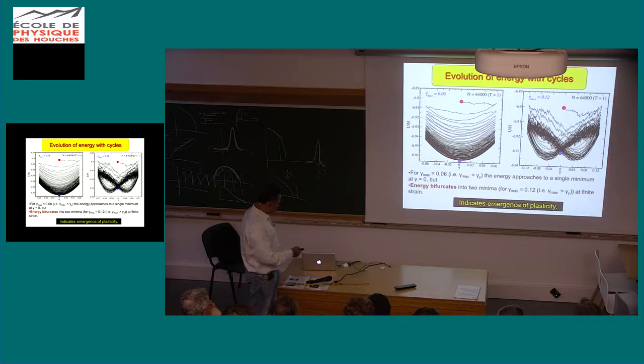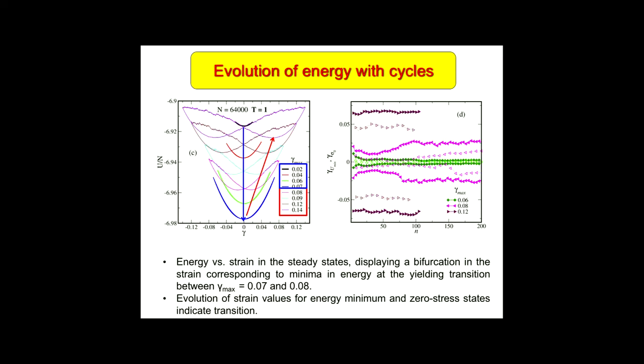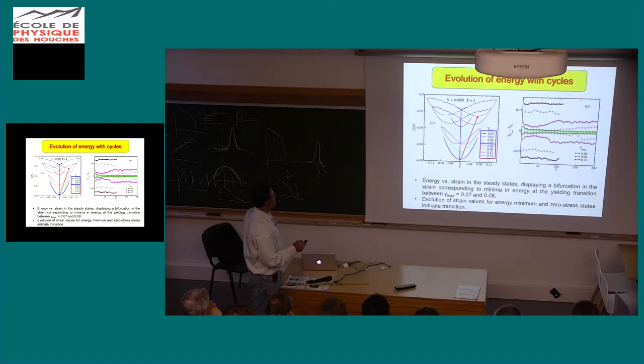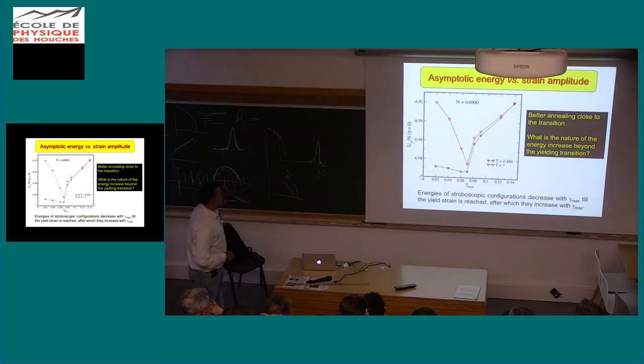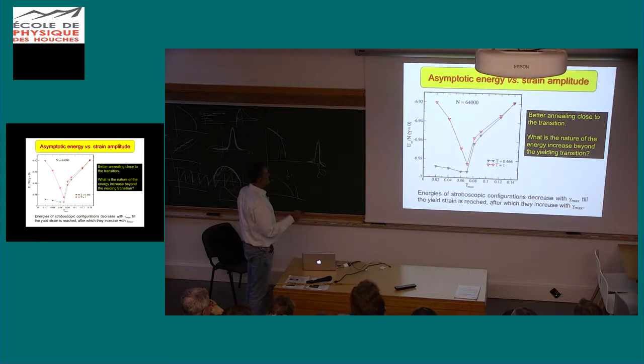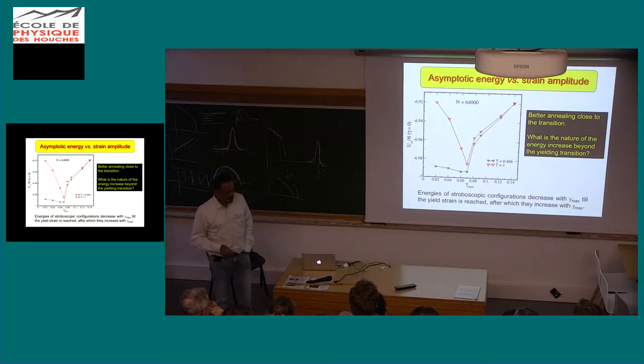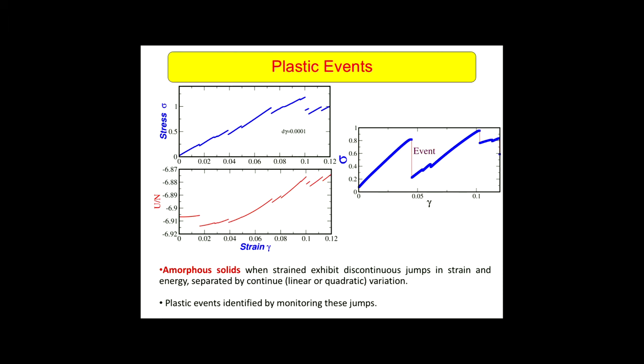Okay, this indicates the emergence of plasticity, and so this is probably a little difficult. If I start from a small amplitude and I keep increasing the amplitude, I go down from the black to red to green to blue, and then I have this change in character, and the energies go up again. And likewise, the strain at which the minimum energy is reached is asymptotic to 0 for small amplitudes, but becomes finite and increases as I go to larger amplitudes. Okay, and this is the picture for the energies. There is the threshold strain amplitude at which the energies are minimum, and so that's a characterization of the transition we're looking at.